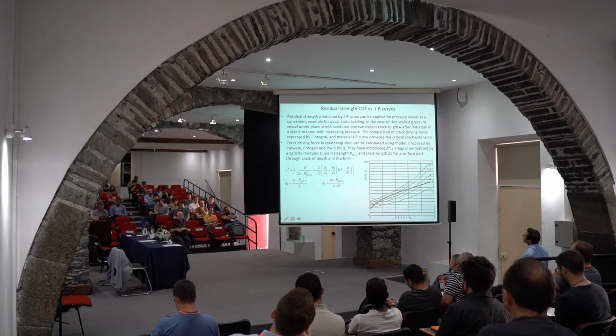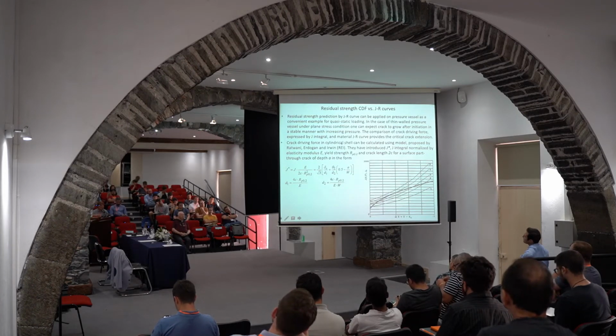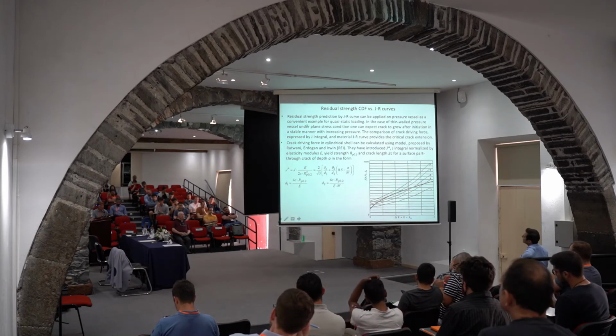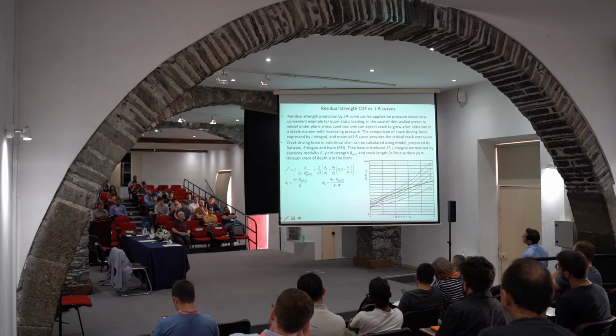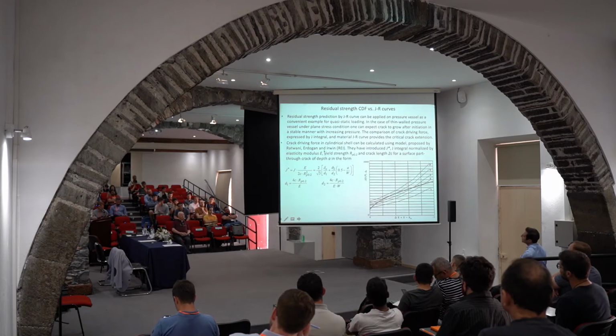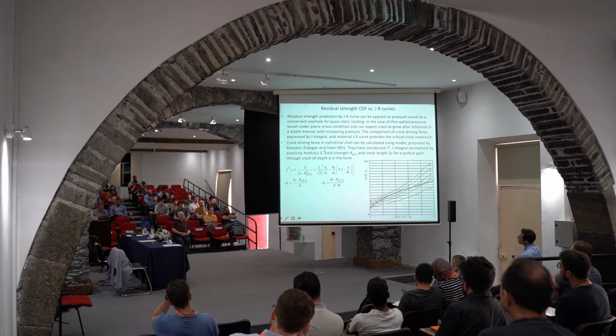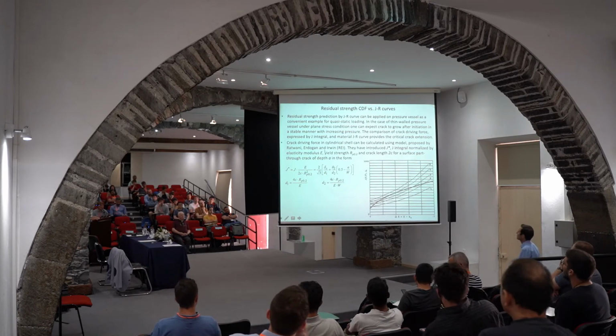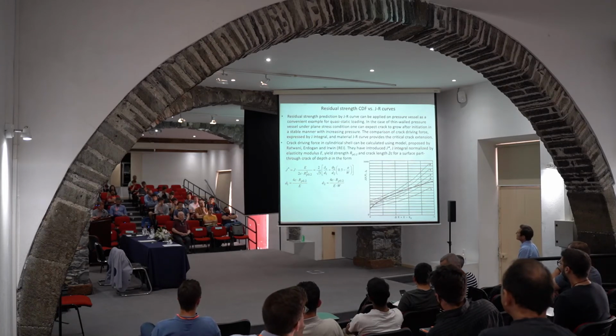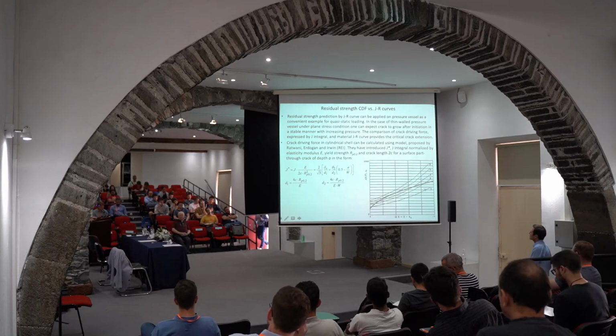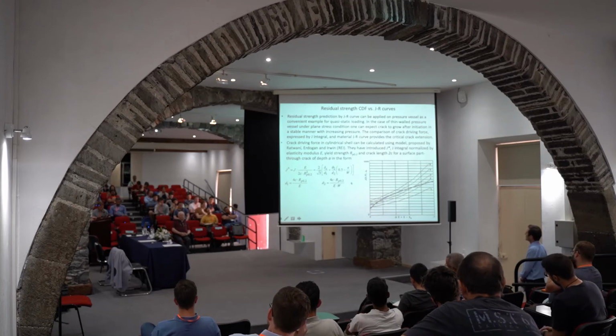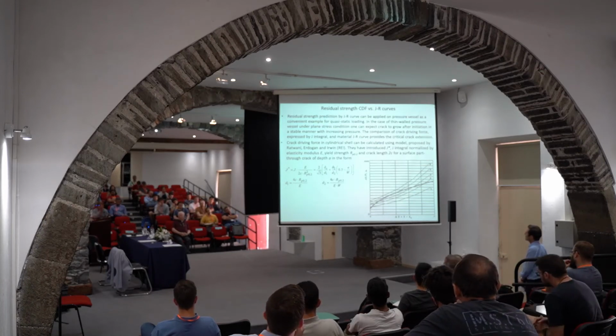As for the crack driving forces at that time, this is early 80s, we couldn't use finite element method, but we rather used a model proposed by Rice, Erdogan, and Irwin, which really produces very good results for cylindrical pressure vessels. It correlates the J integral with displacements and strains, and using it we can produce these crack driving forces here, just schematically shown from 1 to 5. I will show them later on.